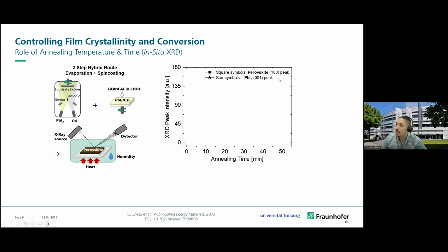So here we will see how the perovskite main peak and the lead iodide precursor peak change depending on the annealing temperature and the time. At 120 degrees, you can see that the lead iodide peak that comes from the precursor is very high at the beginning of the annealing time.